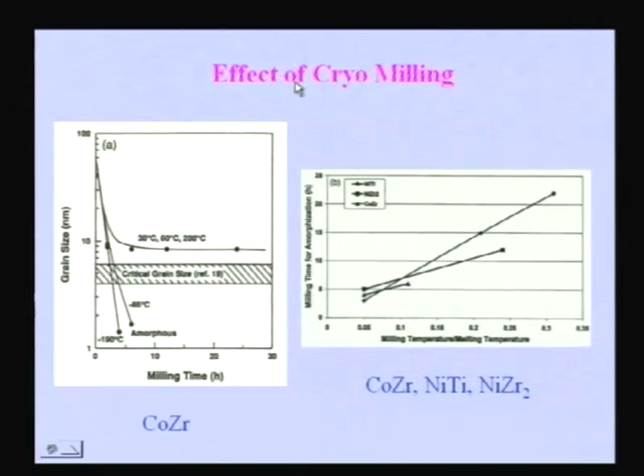And similarly here is an example of the effect of cryomilling. When you start ball milling at room temperature, this is cobalt zirconium, you cannot bring the crystallite size to a very low level. The crystallite size is only about 10 nanometers or so when you ball mill it at 30 degrees or 60 degrees or 200 degrees. These are all milling temperatures. But if you reduce the milling temperature, do cryomilling, for example minus 85 degrees and minus 190 degrees, the rate of decrease in the crystallite size can be very fast. So as a result, you come below that critical crystallite size, so that amorphization can easily occur. So cobalt zirconium can become amorphous very easily.